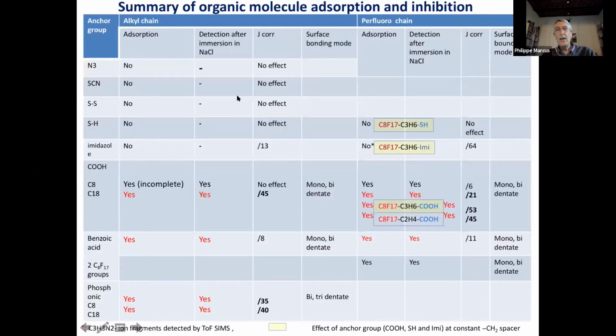So now we can make a summary of what we have done. In this busy table, we have here the anchor group, and we have here the alkyl chain or the perfluoro chain. In this column here, there is the result of adsorption using XPS and TOF-SIMS. And then there is here the result on the measurement of the corrosion current. So let's first look at the adsorption.